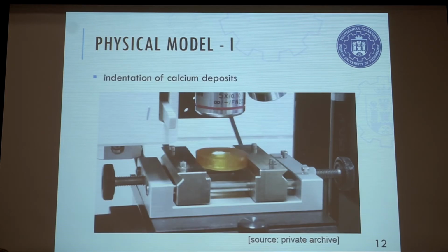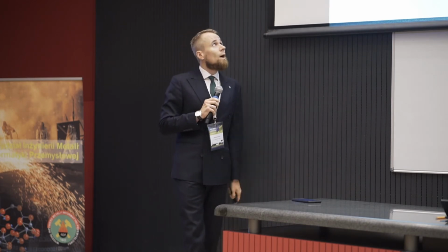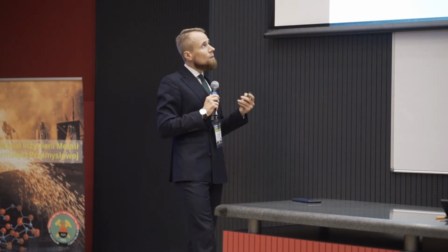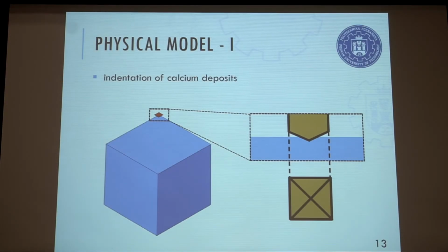Okay, and in order to solve those problems or work with them, I had to prepare two groups of finite element method models. The first one was related with the indentation test of calcium deposit. Those tissues were tested by Magdalena Kobielasz at Wrocław University of Technology in 2014, and I used her data as an input to my inverse problem solution. I had to build a computational model of the test, and in a quite classical approach of inverse problem, I determined the material parameters of those tissues.